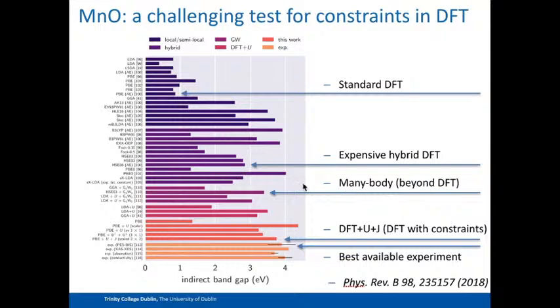And you can even go beyond density functional theory to Green's function-based methods that are getting very, very expensive, and still you do quite a poor job. So this is where we come in my research group. What we've been developing for the last few years are these methods to, on a case-by-case basis, measure the error in density functional theory. We measure the strength of its breach of certain known quantum mechanical exact conditions, and by hand, really with sort of cheeky pen and paper tricks and code hacks, we put the right physics back into density functional theory. I mean, there's a lot of technical detail under the bonnet, and it's actually quite a rigorous thing, but this is where we are in practice. We can get just from this system, and I have many other examples like this.